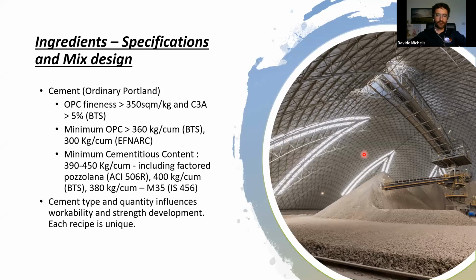And remember that each recipe is unique, so we cannot replicate a single mix design, no matter where, because the performances will change a lot according to the cement type, kind of aggregates, and kind of admixture that we decided to put inside. One recommendation is to avoid high cement content, because if the cement content is too high, we could have shrinkage and thermal cracks, which we want to avoid to have a proper final product.